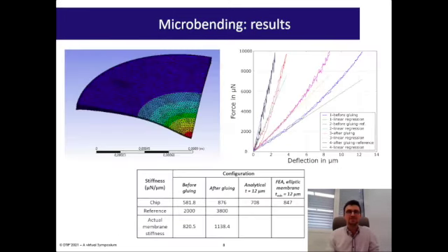That's why, to predict the results we will obtain from our microbending technique, we decided to model our membrane with an elliptic shape using a finite element analysis, depicted here. Here, you have the force against deflection curves that we obtained from the two configurations. For each configuration, we perform a reference measurement outside of the membrane.